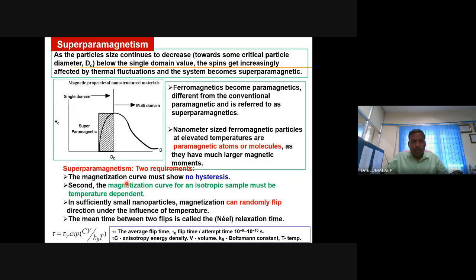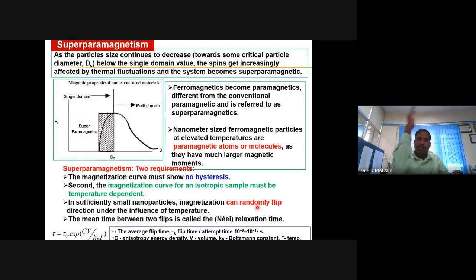And the spins in the domain are influenced by the temperature. When it is temperature dependent, it means that the spin flips also. So when the grain size is reduced down to nano, down to the size of the domain, the spins orienting in this direction, even with a little temperature influence, will go down. And it will not stay there; it will flip back and forth, upward flip and downward flip.